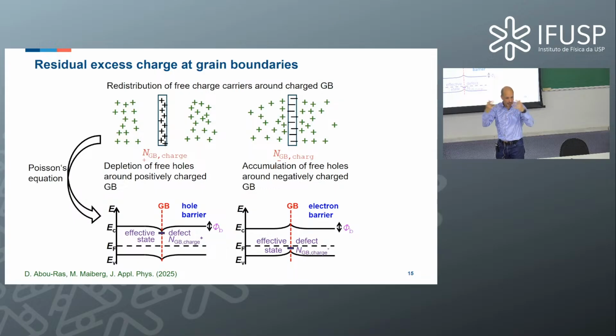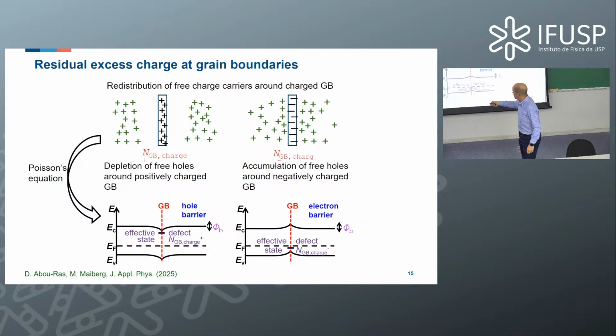So there would be an accumulation of free holes. And this redistribution translates via Poisson's equation to a certain distribution of the electrostatic potential, right? And if the electrostatic potential changes, we have a corresponding change of the band edges. And the band edges here, you can see they form a barrier, which is a hole barrier if the band bending is downward, and an electron barrier when the band bending is upward. Okay? How much it goes up and down, we don't know yet. We will calculate this later.